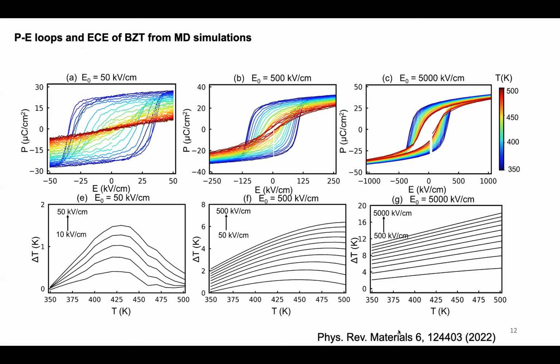Okay, so you start from a more single-domain state, I guess. No. Because otherwise, if you already have more domains, then you pole, but then you remove the poling field, right? And then you measure, you compute the electrocaloric effect. Let me rephrase the question. If you do a simulation with a small volume, then you remove the field in both of them, so you have a single field, right? Yes. That's a permanent polarization. True. So the remnant polarization you are asking about? Yes. How do these two situations differ? The remnant polarization depends upon the temperature. Beyond a certain temperature range, the values will still remain there for the largest poling field.